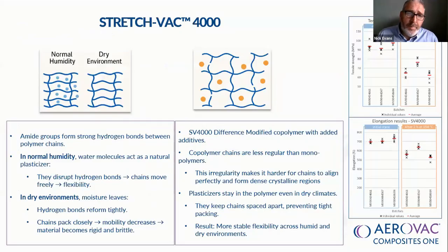So how did Aerovac do that? We took a look at the polyamide groups, and they tend to have strong hydrogen bonds in the polymer chains. In normal humidity conditions, the moisture within the air tends to make the film flexible. It makes it feel soft and easy to work with. But in dry environment conditions, the hydrogen bonds form really tightly, and you get very little movement within the chains, and that makes the film quite crispy and brittle, and it can be difficult to work with. There's always a risk of some cracks, especially in bridging and so on.